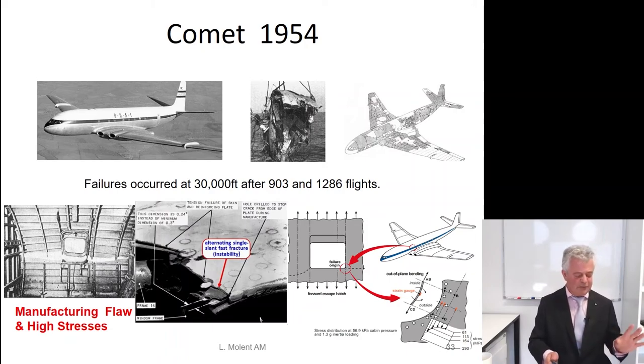Fatigue failure occurred on the first commercial pressurized airplane, the British de Havilland Comet, back in 1954, where two airplanes were lost. Very long story. Why did this occur? Yes, it was the first pressurized airplane. That gives you a hint. The subsequent investigations showed that, in fact, it wasn't the windows per se, but the little windows used by the navigator up here that suffered from fatigue. And it was subsequently shown that, oh dear, the stresses due to the sharp edge here were very high, much higher than was anticipated. Number one, high stresses.